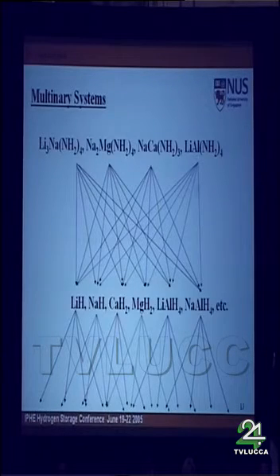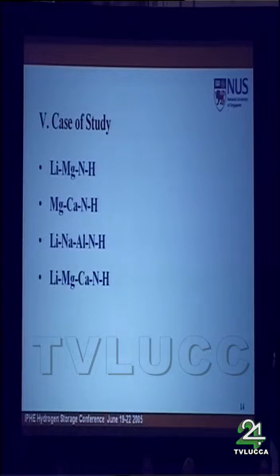I would like to point out that this approach is one of the few approaches which can be adopted in materials engineering. In this approach, we change different amides and hydrides. We can also change the chemical composition of the nitride and also the amides. By such chemical modification, we can also alter the thermodynamic parameters of the system. Therefore, perhaps we can get a very good hydrogen storage system. In the following part, I would like to show a couple of recent examples which show quite interesting performance in hydrogen desorption and also reversibility.